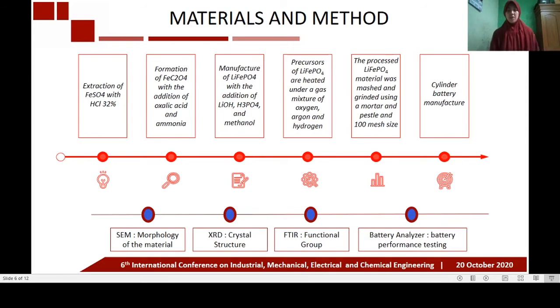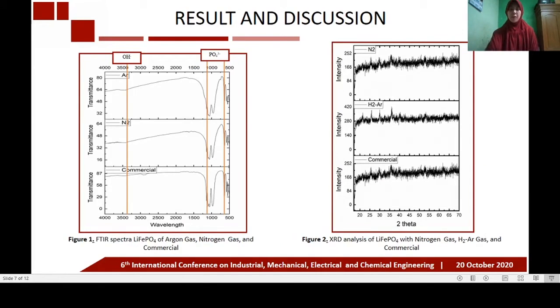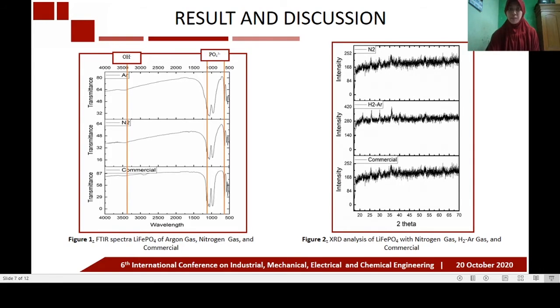The lithium iron phosphate research studied its morphology with SEM, its crystallinity with XRD, and the functional groups with FTIR, and battery performance was tested using a cylindrical battery. From the FTIR results, two groups were observed: the hydroxide bond and the phosphate group. The hydroxide bonds appear in the anti-symmetric stretching mode range of 3000–3500 per centimeter, whereas the phosphate group appears in the range of 1000–1200 per centimeter and 400–560 per centimeter.